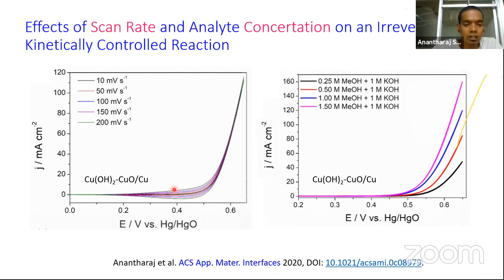So with a single figure, you can actually witness two different reactions: a diffusion controlled self oxidation of the catalyst material, and a kinetically controlled oxidation of methanol. So that's how scan rate affects the diffusion controlled process, and that's how it doesn't affect a kinetically controlled process.